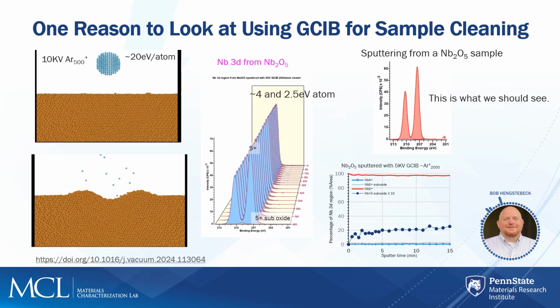So now we're going to talk about what happens when we're using the GCIB cluster. Again, we're going to be looking at a simulation here, and this is a simulation that someone else did, so there's a reference to it towards the bottom here. It's a 10 kV argon, about a 500 atom cluster. The clusters that we're actually going to be using more in the lab are going to be much larger, anywhere from 1,000 to 2,500 or 3,000 atom clusters. But in this example, you'll see that instead of getting large amounts of subsurface damage, you essentially push the material off to the edges, and then you get some sputtering. Almost all of the argon that actually hit the surface was removed during the initial breakup and collision of the material. And you'll see that again in that picture.